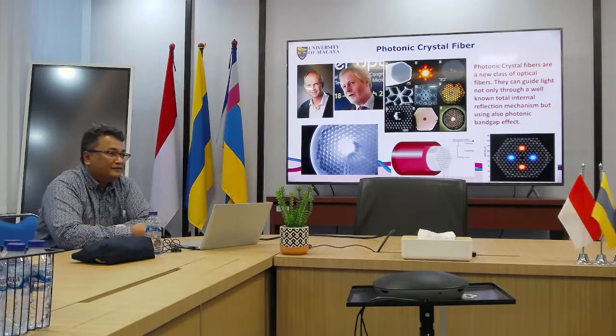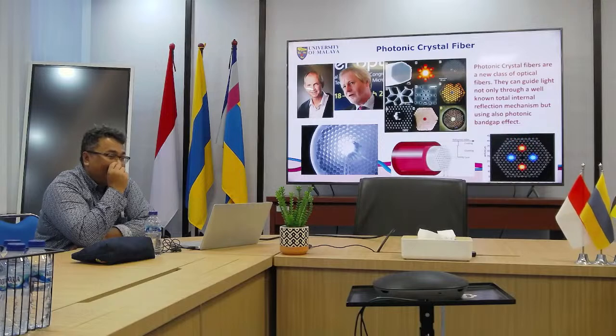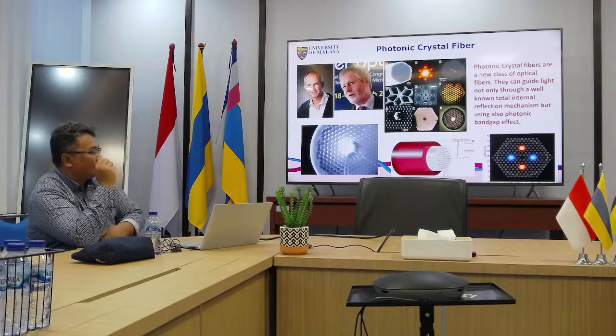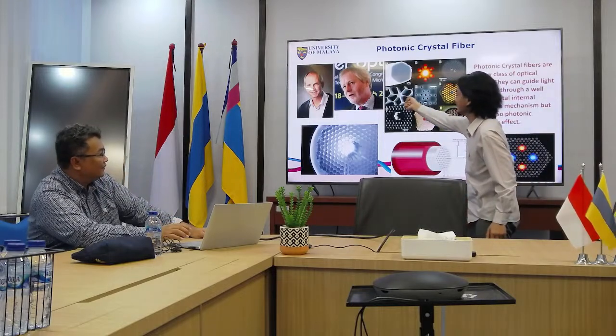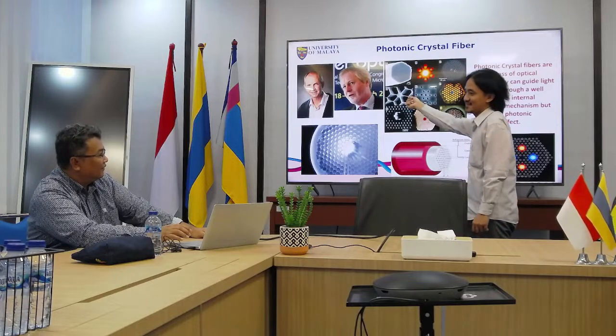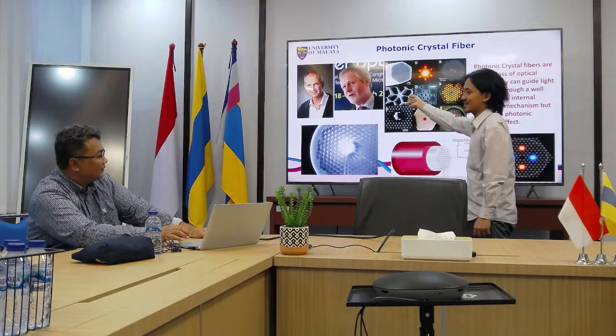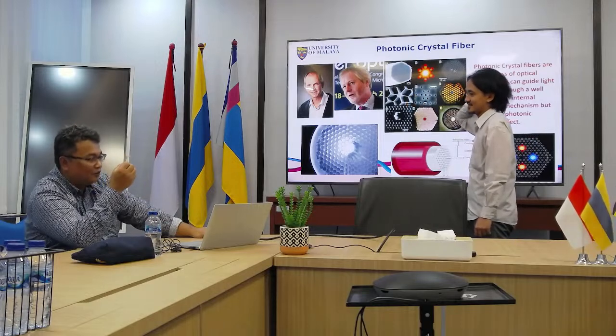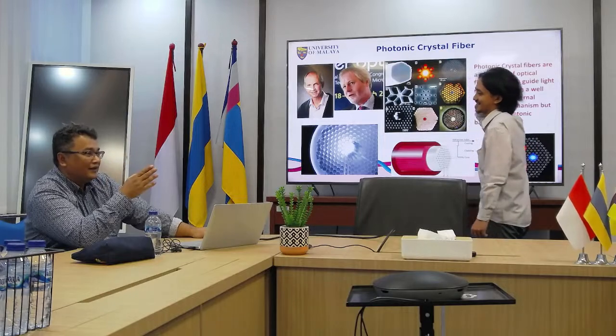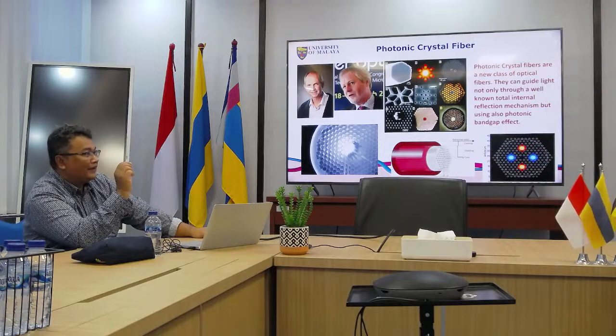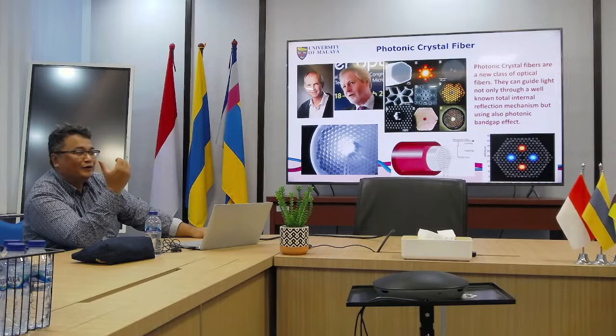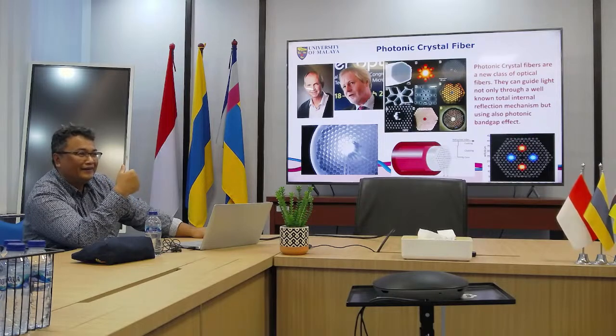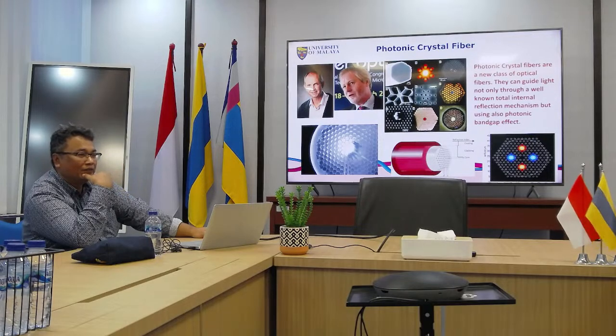I see. So this is basically different from electron transfer, right? So it seems the defect should not have much effect on the light transfer, I think. The defect in silicon dioxide, for example, if we put in some oxygen vacancy, will it affect the light transfer? No, because we want the structure to be transparent. If you have a defect, you get a certain band gap here, and that band gap can cause absorption. So they can absorb the light and give loss. So that's why the silicon dioxide should be pure, right? Yes, it should be pure.